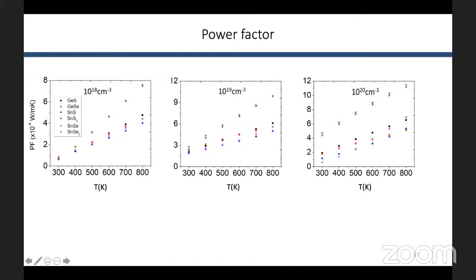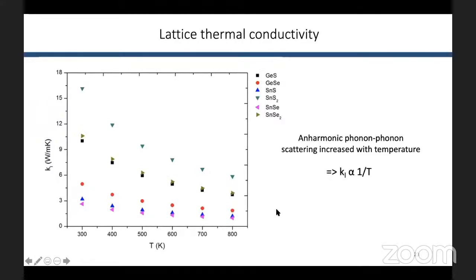However, we need to calculate first the lattice thermal conductivity. And in this case, the lattice thermal conductivity decreased monotonically, and this is because as temperature increases, anharmonic phonon scattering becomes more intensive. And all of the 2D materials studied here have relatively low thermal conductivity if we compare with other kinds of materials like graphene and molybdenum disulfide, and others, making them promising candidates to have a higher ZT.